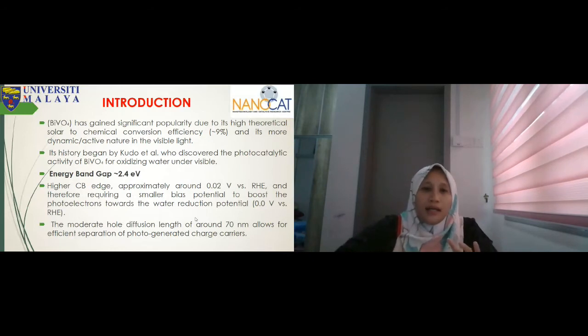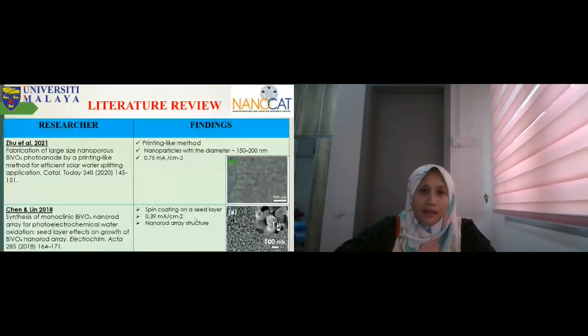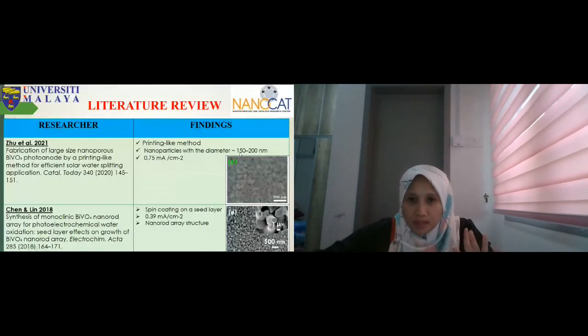Next, several research papers have been done by other researchers. The first one is Zhu et al., published in Catalysis Today. He used fabrication of a large-size nanoporous bismuth vanadate photoanode with a printing-like method, and it can be observed here. They have a nanoporous structure, the diameter is 150 to 200 nanometers, and the photocurrent density achieved 0.75 milliampere per square centimeter.